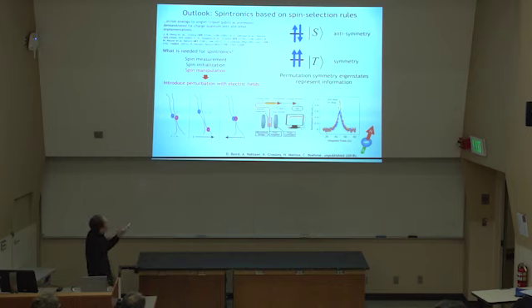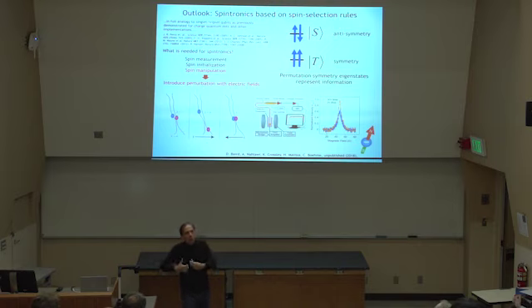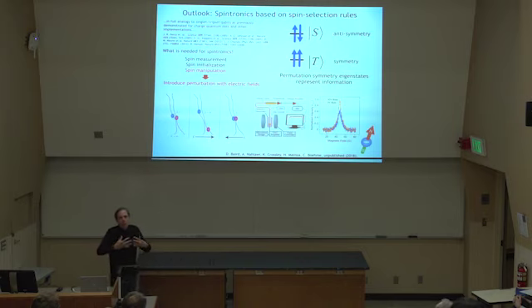If this is true and corroborated, that's only a proof that the electric field influences your signal, not that it manipulates spin. Then you can think about adiabatically changing the distance between your spins and controlling interaction Hamiltonians, such as dipolar interaction, adiabatically with electric fields, and then using this for a gate-controlled, electric field-controlled spin manipulation of these permutation symmetry states in these materials.